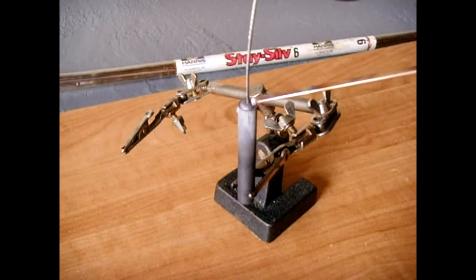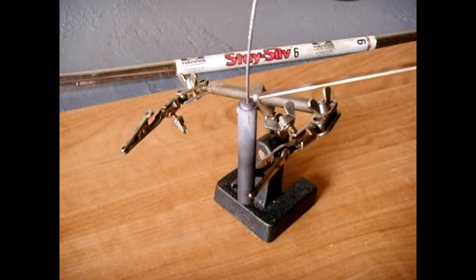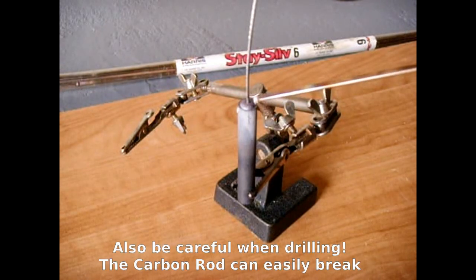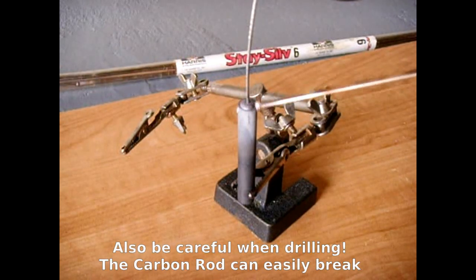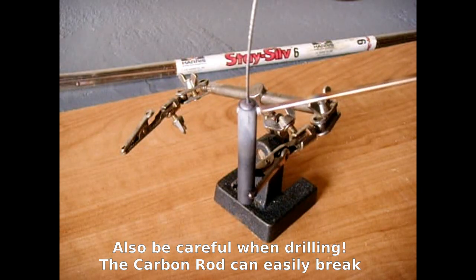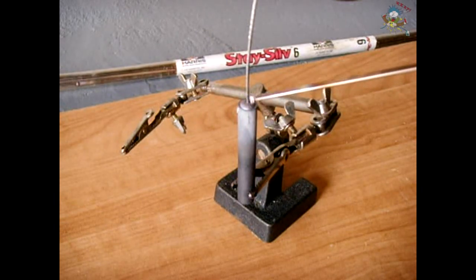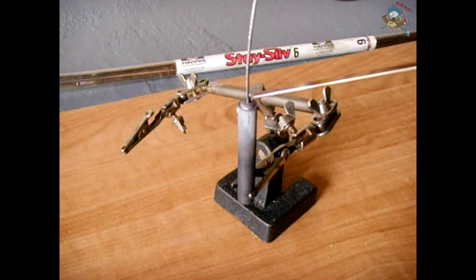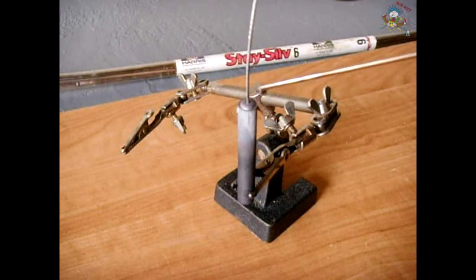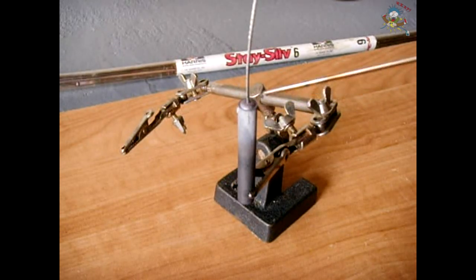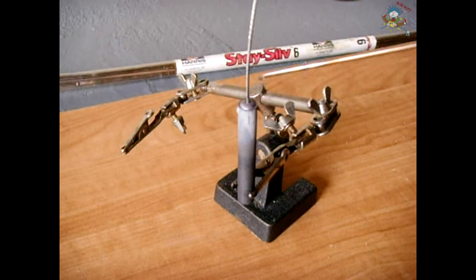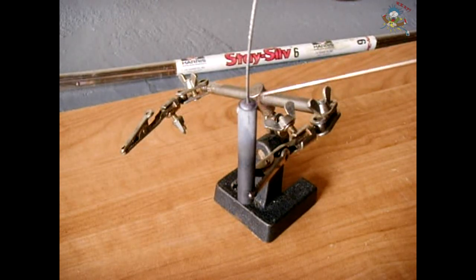When you drilled out the carbon rod, just make sure that the smaller hole in the center is no more than about a sixteenth of an inch deeper than the larger hole that you drilled. You want the wire to go a little lower but you don't want it all the way sticking out on the opposite side. Just make sure that the loop end is securely encapsulated in that molten material. Now once this cools I will extract it from the carbon rod and you'll have a perfect end which will not pull out. I have not had any of these pull out yet.